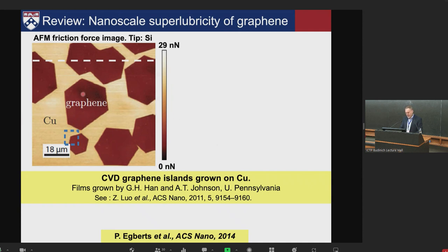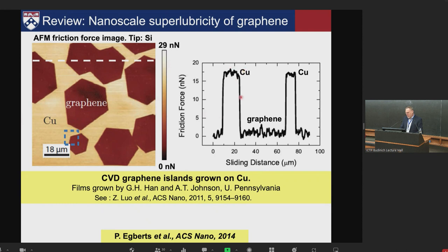These are some monolayer graphene islands that he grew using CVD, which we looked at. This is now 10 years ago or so, but I really like this example because what we've got is a copper surface and then just a monolayer of graphene on top, and this is a friction force map. And you can see as you slide across, you get an order of magnitude reduction in the friction between the copper.